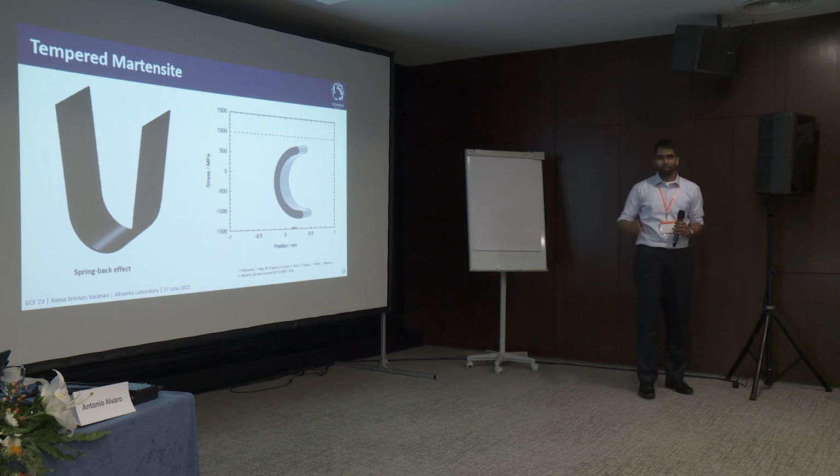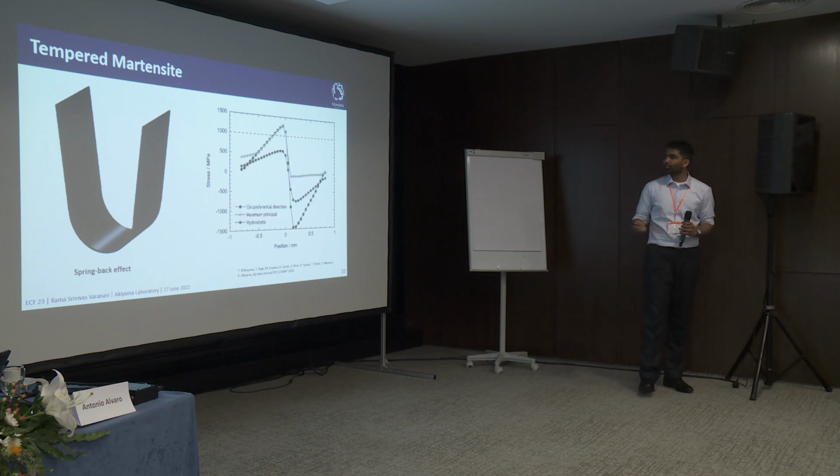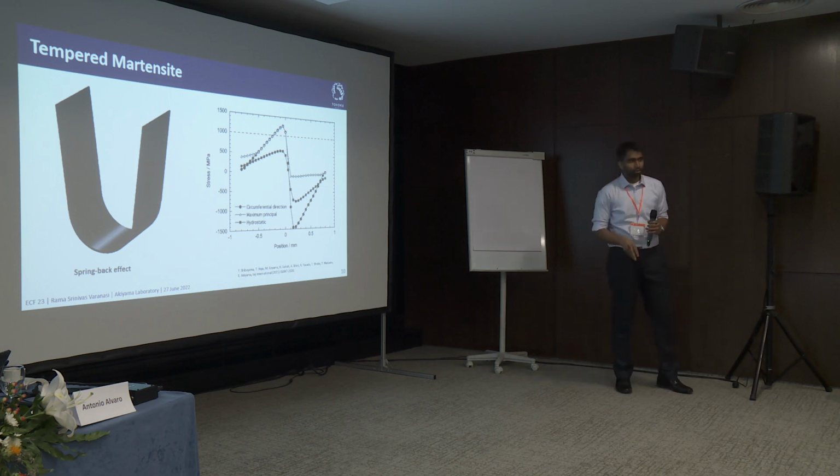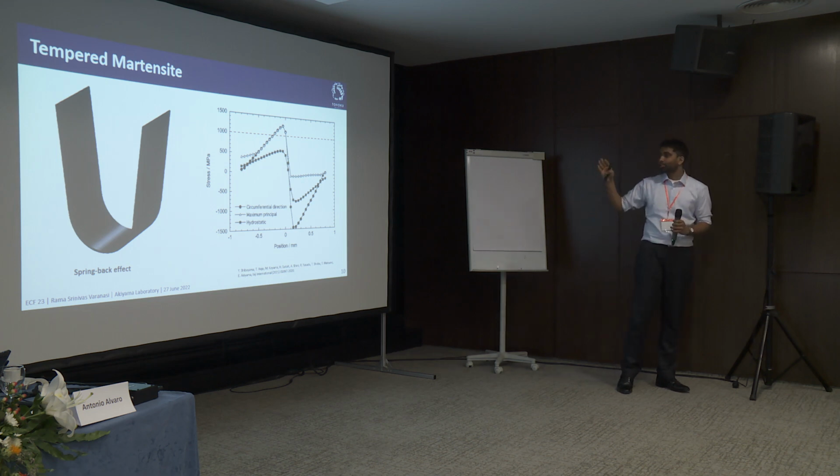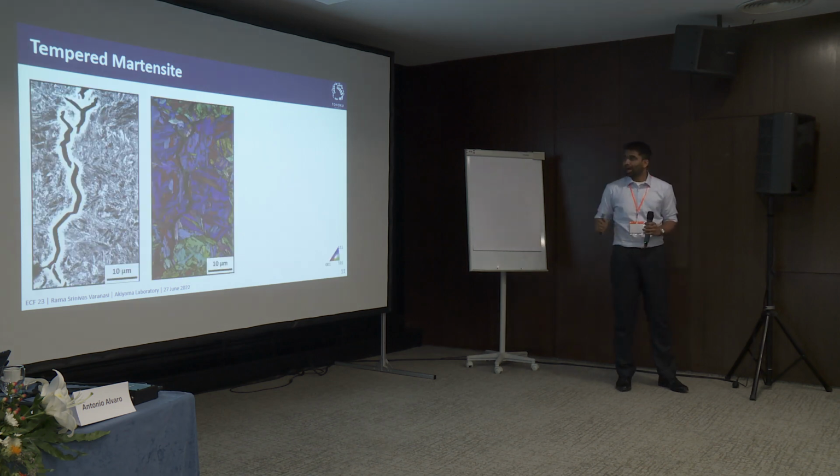For the applied stress of about 1000 megapascals, we can see that the stress at the surface is quite low. In fact, the highest stress concentration is not exactly at the center, but very close to the center. So when we charge it with hydrogen, the hydrogen diffuses to this highest stress region, and therefore we have a subsurface crack initiation. The second aspect is the crack propagation.